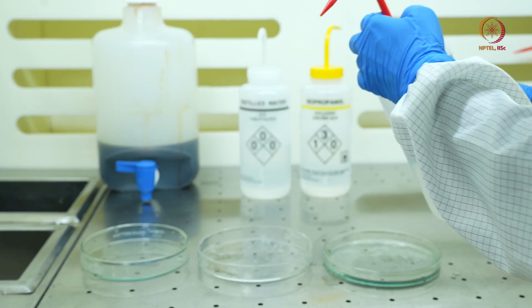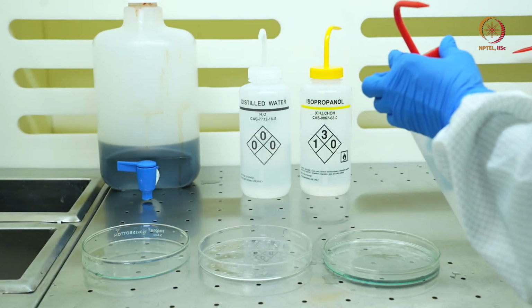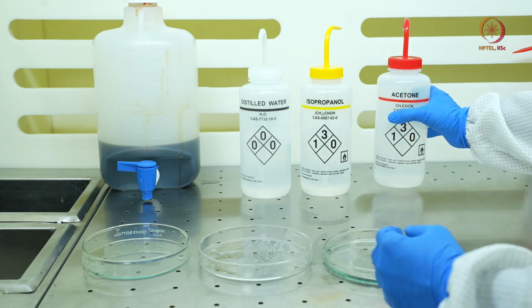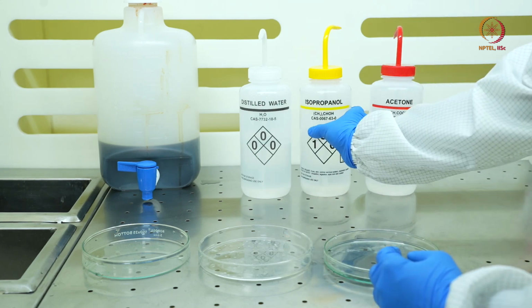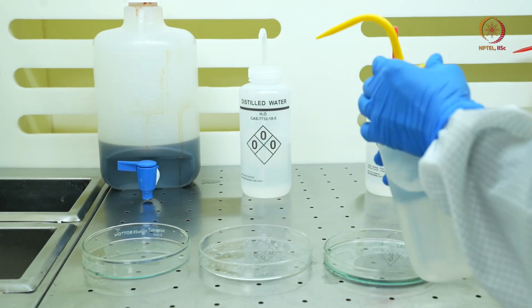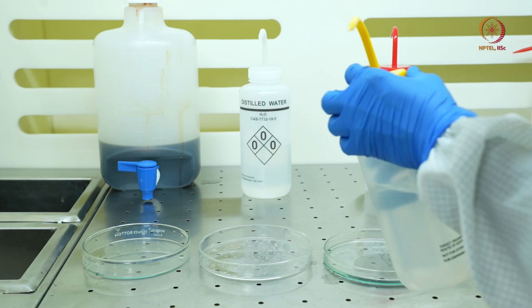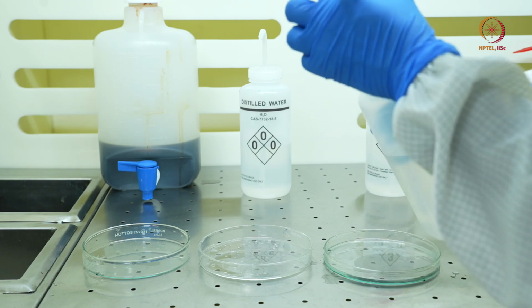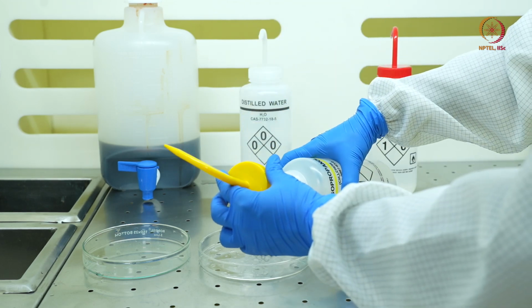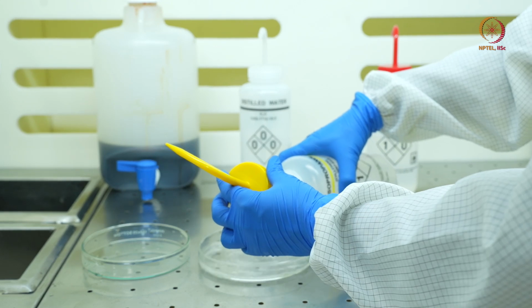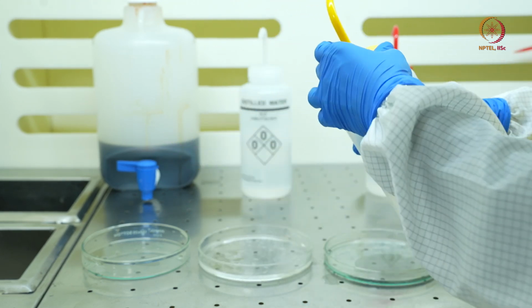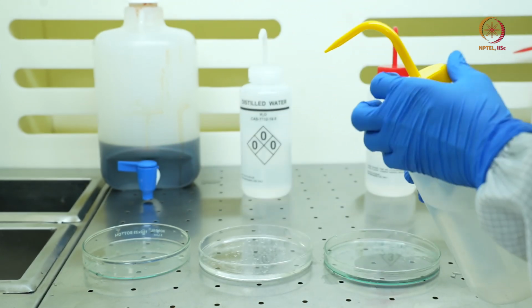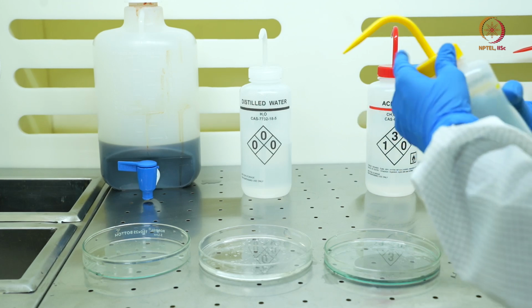Make sure that the quantity of chemicals you are using is just enough so that your sample is completely submerged inside. If a part of your sample is floating outside or not properly submerged, it is possible that the cleaning won't be proper and you will have some contamination left.